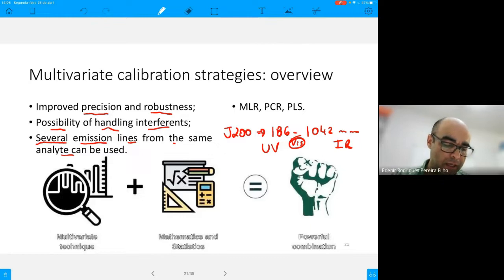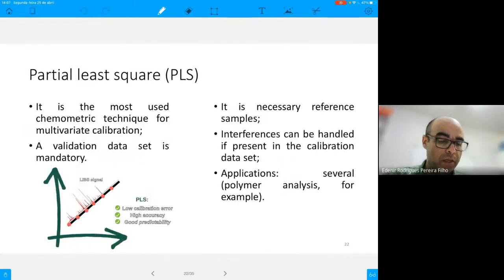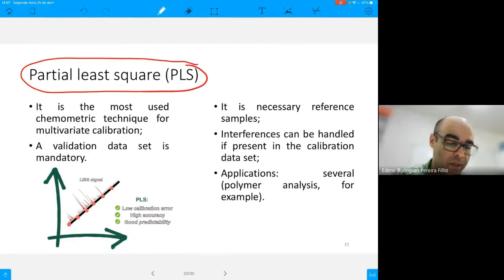Okay, and we can also use several emission lines. For example, chromium, iron. These analytes have more than 100 visible emission lines in this range using the J200 instrument. The most used multivariate calibration is PLS, partial least squares. Is the most used. We can use several emission lines.